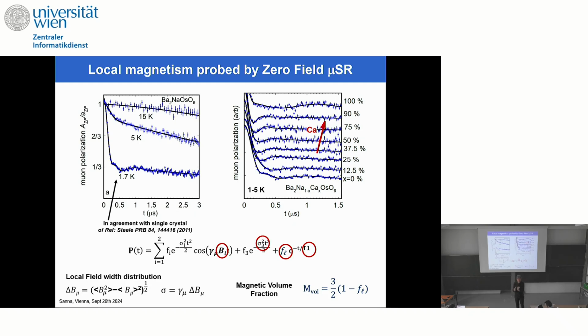Because the same is seen in the single crystal and in the powder, so it is not an effect of the powder nature of the system. Okay, so these are the information related here and here. This is related to the oscillation, related to the magnetic behavior of the sample.